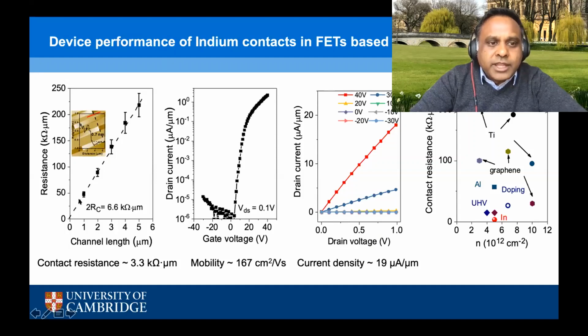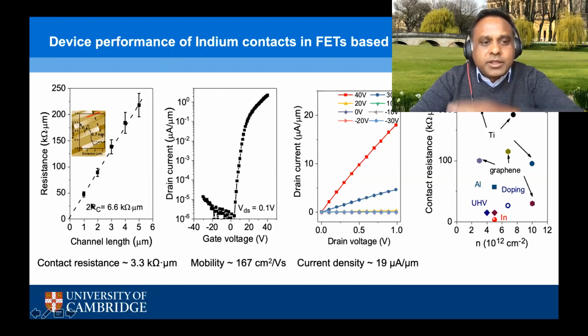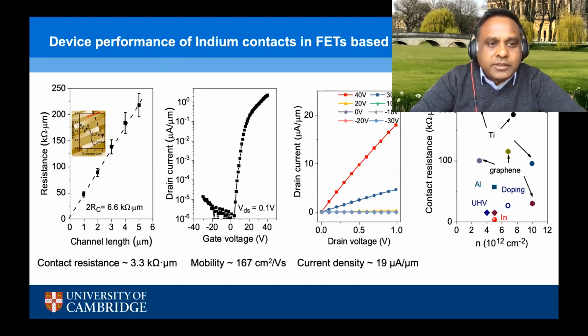This is a transfer length measurement of resistance as a function of the channel length. One can see that the contact resistance in this case of indium contacts on single layer MoS2 is around 3 kΩ·µm. This is still substantially larger than what one gets in silicon, or what one gets by phase engineering, but this is amongst the lowest values that have been measured so far.